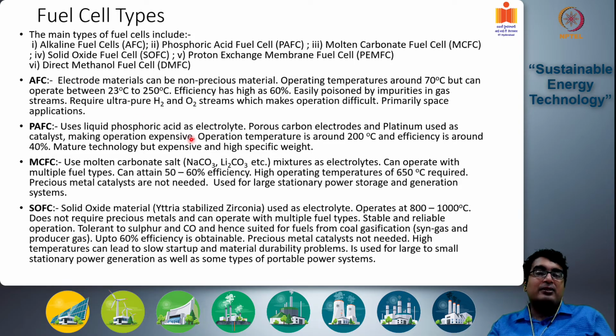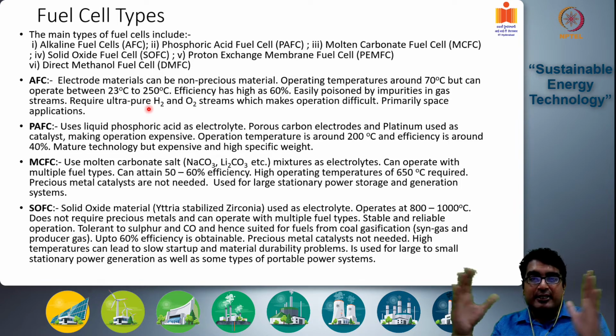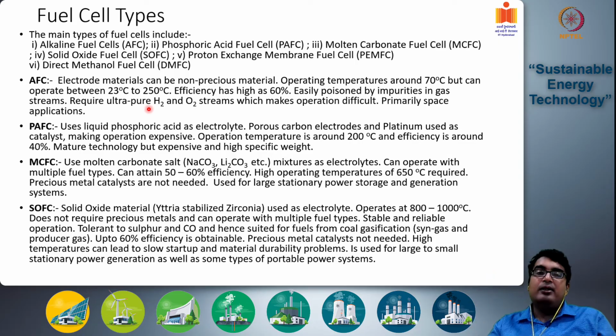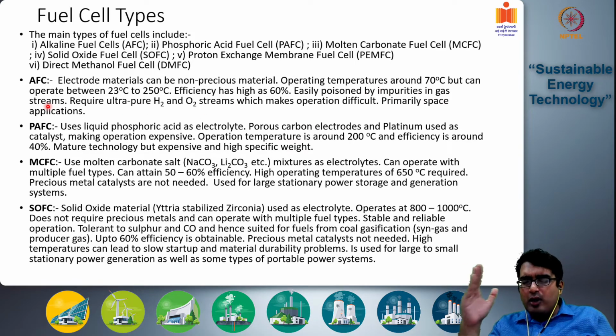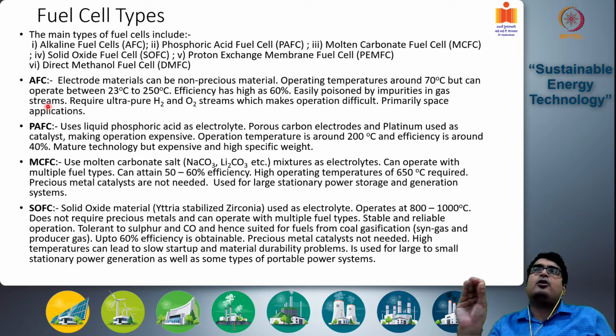So the alkaline fuel cells we already discussed. Electrode materials can be non-porous precious metal, non-precious materials. So you do not need platinum, for example. Operating temperature is also reasonable, around 70 degrees, but can operate over a wide range, 23 to 250 degrees centigrade. Efficiencies can be as high as 60% even for a stack. However, it is easily poisoned by impurities in the gas streams. So it works with ultra pure hydrogen and oxygen streams. Air does not work, which is a huge problem.